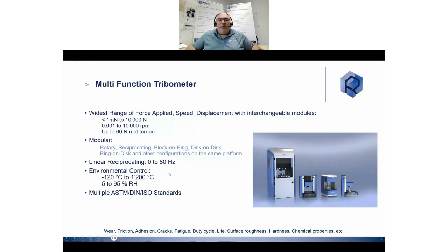We have a linear reciprocating going from 0 to 80 hertz of frequency. Naturally, a lot of environmental control, from minus 120 and we can go up to 1,200 degrees. And we have also some humidity chamber to go from 5 to 95% of humidity.